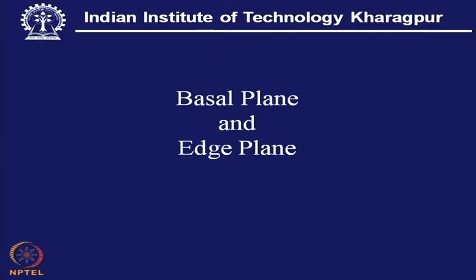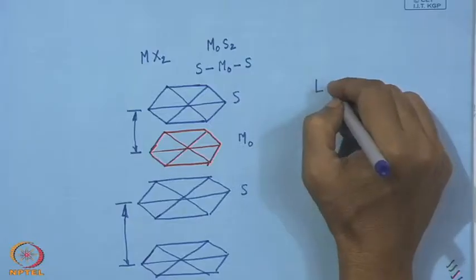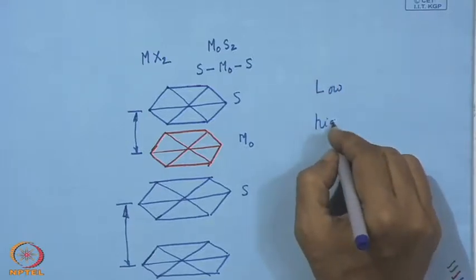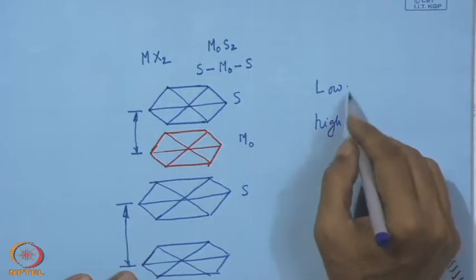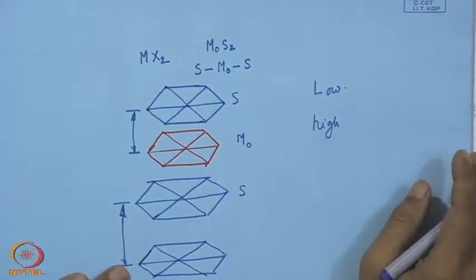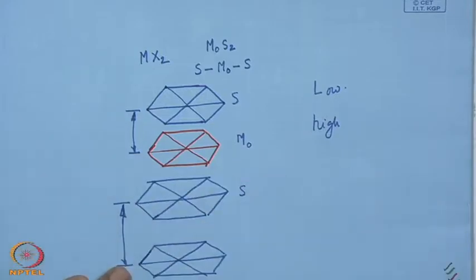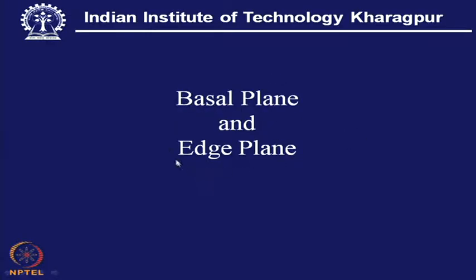Now, here what we can see, two planes are there, the basal plane and the edge plane. These are to be taken into consideration, because the orientation of this plane is extremely important to have a very low value of friction. Low value or high value, good performance or poor performance, this too will depend upon the orientation of this basal plane or this edge plane. Now, let us look at what is meant by this basal plane and edge plane and how they should be oriented.